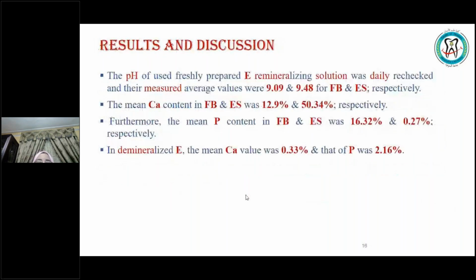The obtained study was done first for the pH. As we have explained in the methodology, the pH is a very important and crucial issue to be considered in our study, starting from the normal saliva, the demineralizing solution, the remineralizing solution, whether fish bone or eggshell. So the pH of the freshly prepared enamel remineralization solution was daily rechecked, and the measured average value was 9.09 and 9.48 for the fish bone and the eggshell respectively, where we can note that the eggshell is a little bit higher than the fish bone.